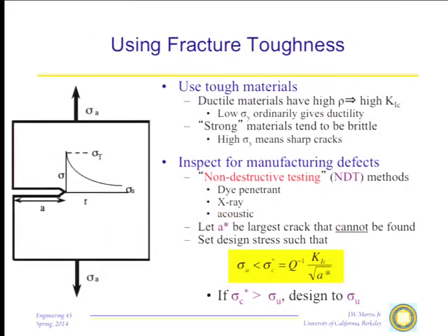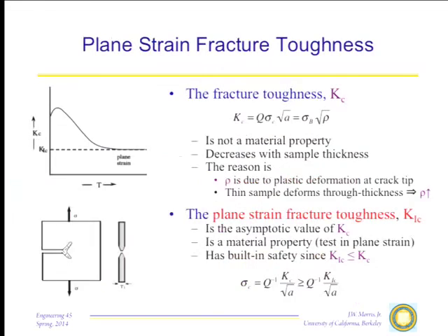One thing we can do is use tough materials. Most of the parts of your automobile, and many parts of aircraft, helicopters in particular, are actually not designed to fracture toughness at all. And the reason you can avoid designing them to fracture toughness is this: suppose you take apart some gear or shaft in your automobile, and you put in the fracture toughness, consider the worst crack that could conceivably be there, and calculate a stress. You don't have to worry about this crack instability stress unless it is less than the ultimate tensile strength. Because when you reach the ultimate tensile strength, the thing's going to break in plastic deformation, and it doesn't matter that if you could continue the stress, it might propagate a crack, because it's already broken.